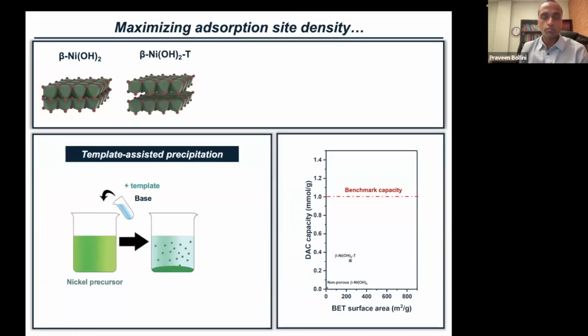So what we'll do next in order to modify this is we use a template. Specifically, this is an octylamine template that's used to create porosity in your nickel hydroxide sample. And you create, of course, as you can see in the plot on the right, both some porosity as well as a direct air capture capacity. The protocol that really unlocks high surface areas and carbon capture performance in our case is using carbonates to form layered double hydroxides, and then using a solvent, could be something like ethanol, that in fact delaminates these layered double hydroxides and creates a high amount of surface area.